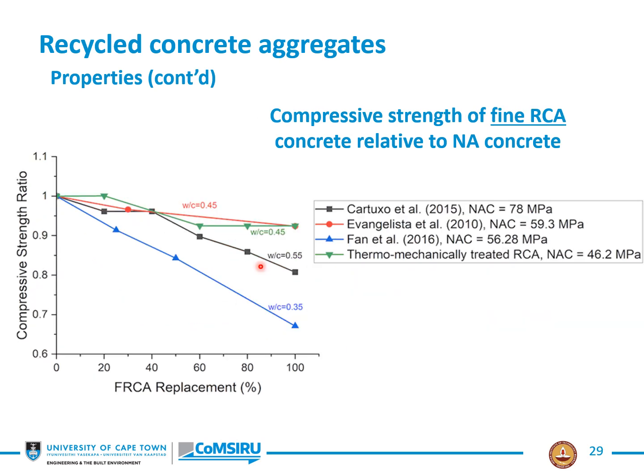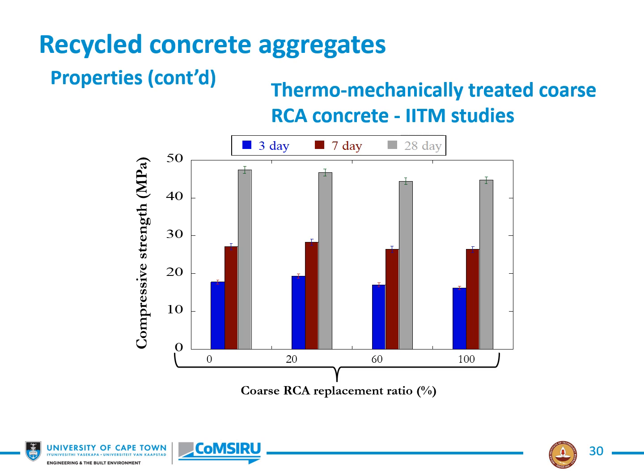For fine recycled aggregate, the same picture emerges, although the data is more sparse. Here you can see again that it's possible to, even at 100% replacement, get reasonable values for compressive strength, but at the same time it's possible to get large reductions in compressive strength. And so what this tells us is that every case needs to be considered on its merits and has to be judged accordingly. Here is an example of a thermomechanically treated coarse aggregate from IITM.